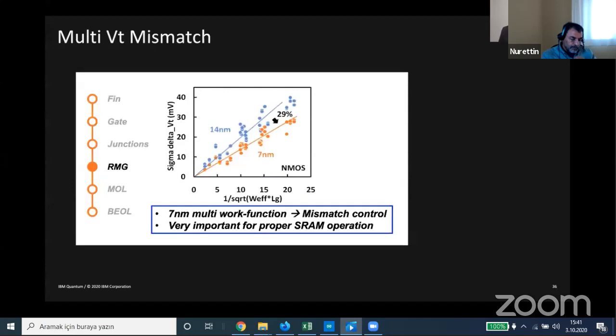Shown here is the mismatch data as described earlier. You can see less variation or sigma VT versus 14 nanometer, comparing the blue here to the orange data. And this is plotted as 1 over square root of WL. This is like the well-known Pelgrom plot for looking at mismatch.